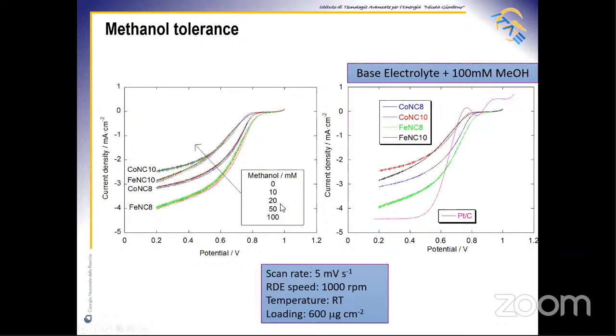In the base electrolyte with 0.1 molar methanol concentration, the commercial 30% platinum carbon catalyst shows an evident methanol oxidation peak during the experiment. Thus, in this condition, FeNC8 is the most active catalyst because it shows onset and halfway potential larger than platinum carbon.